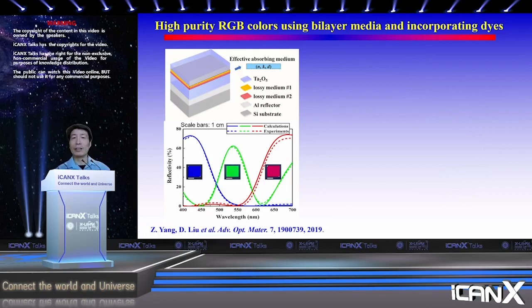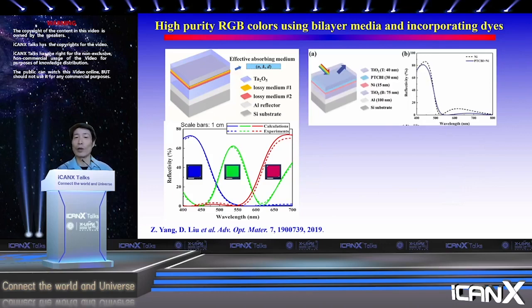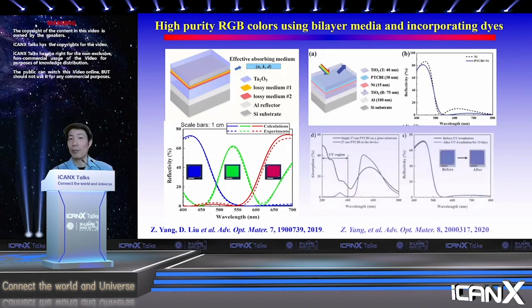Now, earlier I mentioned the dye has a UV sensitivity. It can degrade, right? But UV dyes, they do have absorption. So here we put a very thin layer of dye into the stack to perform the absorption that's needed. Okay. And again, you can get very pure color. And then another nice advantage is that even the dye is only 30 nanometer, so if you put this dye on a piece of glass, you hardly see any color because it's so thin. But putting this optical cavity, it significantly enhances the effect because light travels many bounces. Another thing is that although the dye is sensitive to UV, in the cavity, the UV absorption by this dye is much, much weaker. So you can see after 15 days exposing UV light, the color doesn't change. So it's a combination of this hybrid structure that could actually make it work too.